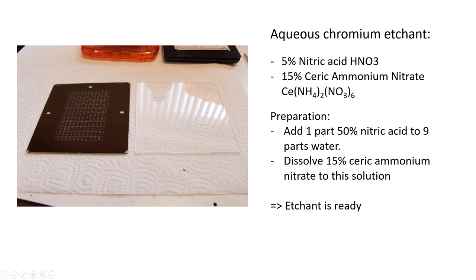The best chromium etchant you can work with is a solution of ceric ammonium nitrate and nitric acid. The concentrations, which I indicated here, are not very critical for your application, because it is just removing chromium from the photomask.